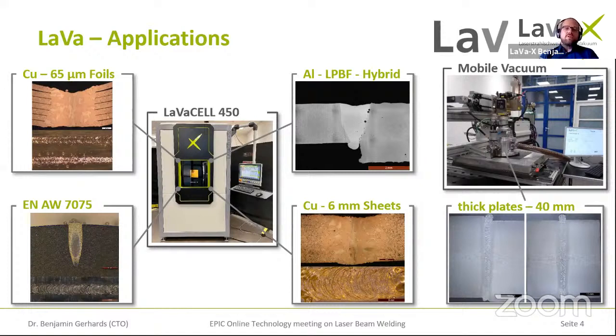We also conducted experiments on additively manufactured aluminum, displayed in the upper right picture. Usually you have the problem that many pores are created, because the material is very susceptible to the creation of pores in the weld seam. And as you can see, there are only pores on the fusion line on the right side, but no pores or nearly no pores in the weld seam itself.